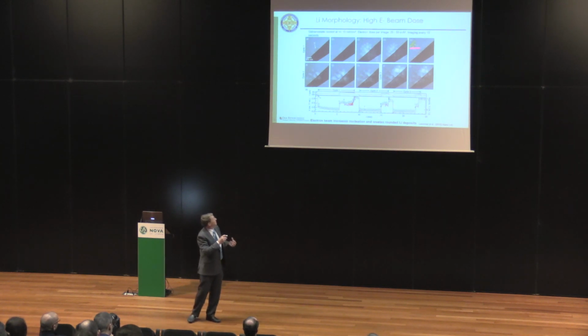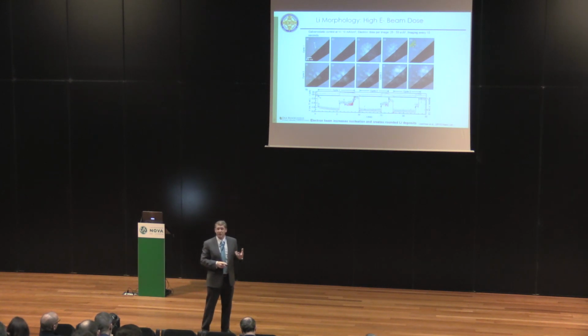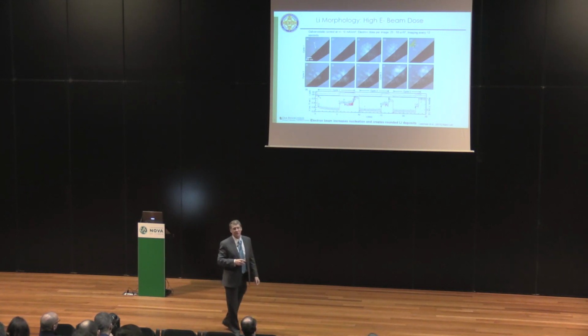When they do a strip cycle, they strip, and you see there are a few areas that are light here. In those light areas, it's where the lithium was trapped, so they're not able to actually access all of that lithium. And you'll see a shadow, right? There's a little bit of this shadow structure here. This is the SEI layer.